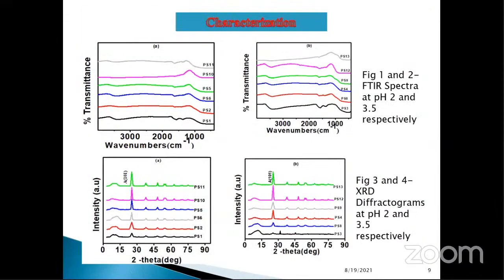The characterization part includes, as we can see in figures 1 and 2, FTIR spectra at two different pH values, pH 2 and pH 3.5. We can see very clearly that the silicon oxygen silicon stretch peak at 1049.31 per centimeter has been completely lost, which indicates that the intercalation of titanium 4 ions, metal ions, into the interlamellar space of the clay has been made possible.